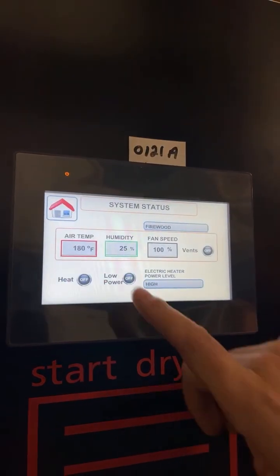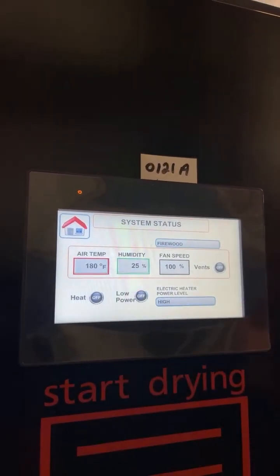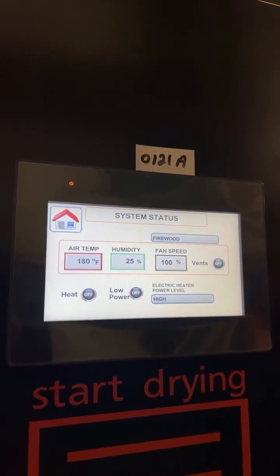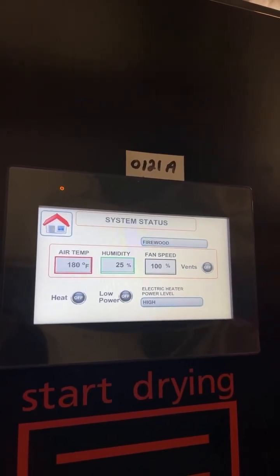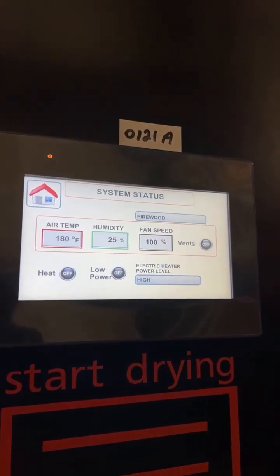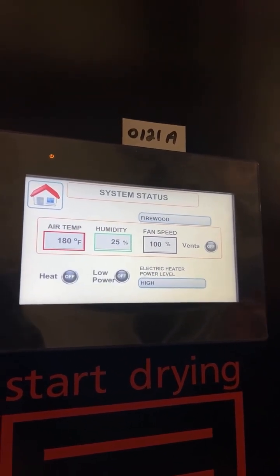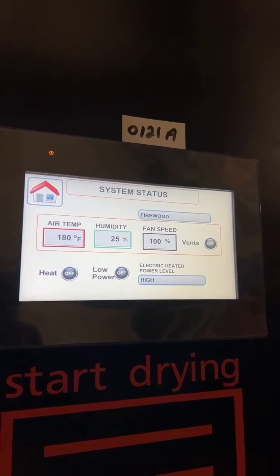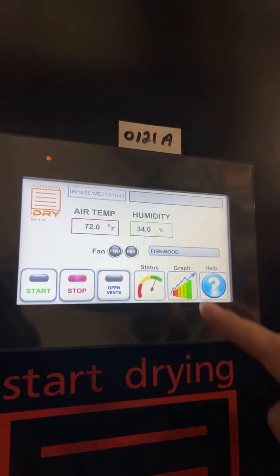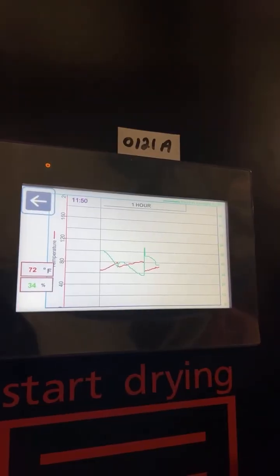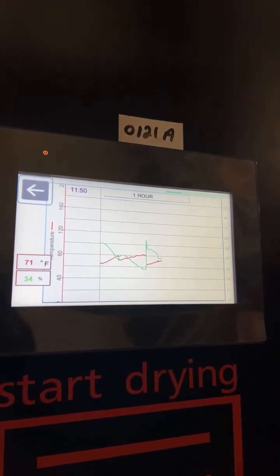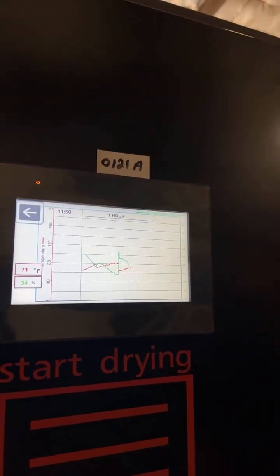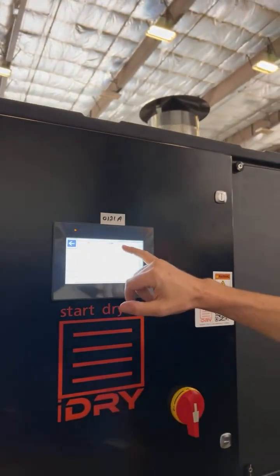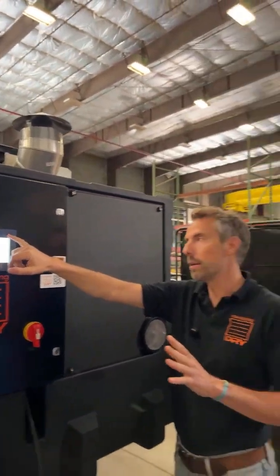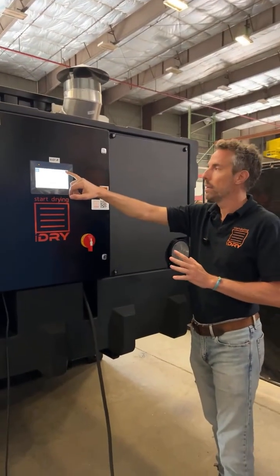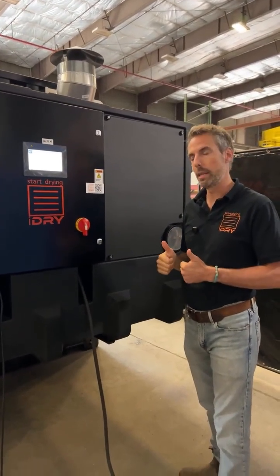We can also set the settings manually if we want to set the air temperature and the humidity. For drying firewood, 25% humidity is as low as you really need to go. That's relative humidity, so that's the air humidity, not the wood humidity. But that will easily get you down to below 20% moisture in the core of the firewood. We also have a process graph so you can see what's been going on. This is really useful if you're trying to prove to your customer, or maybe the USDA inspector, that we have actually reached a minimum of 160 degree air temperature.